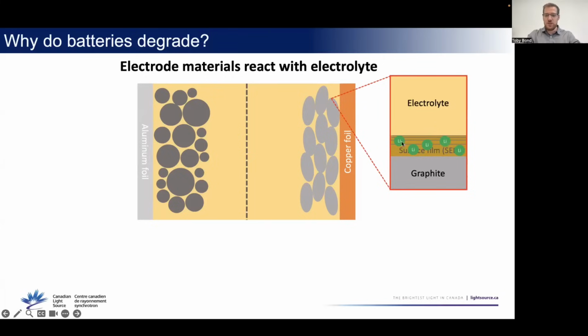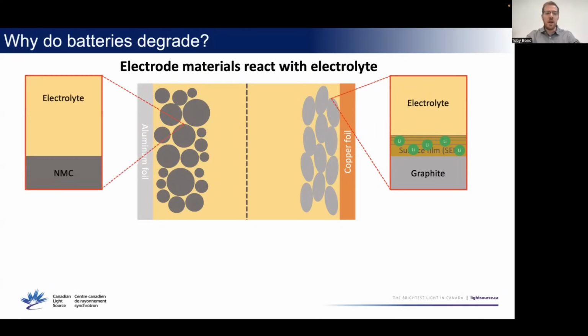The reason this causes degradation is because lithium ions actually get trapped. They get incorporated into this film, and so you can't use them to charge and discharge the battery anymore. And each of these lithium ions that you lose means that you lose one electron that can't go to power your car anymore.